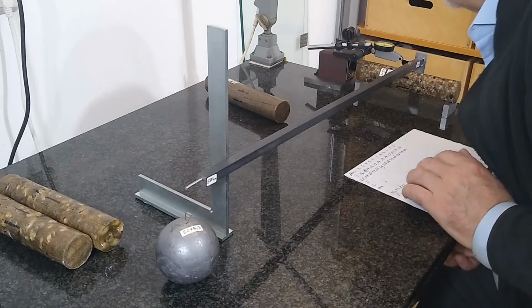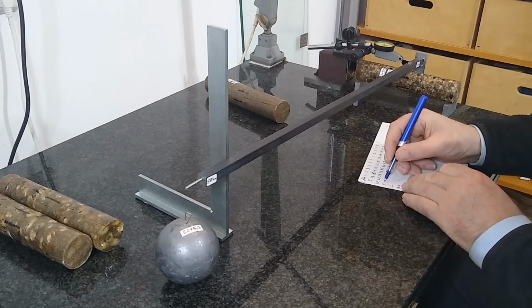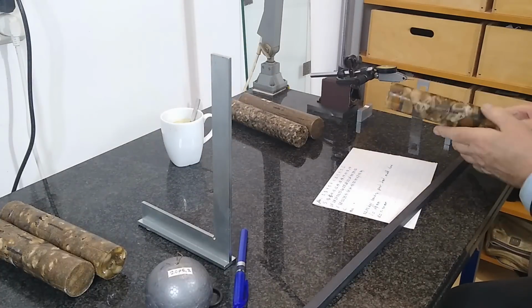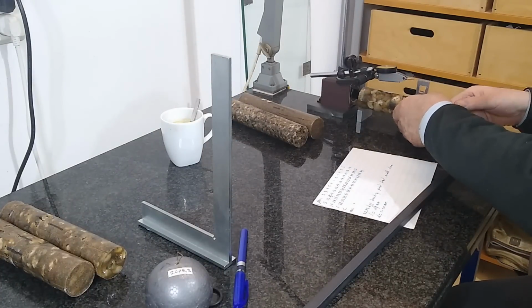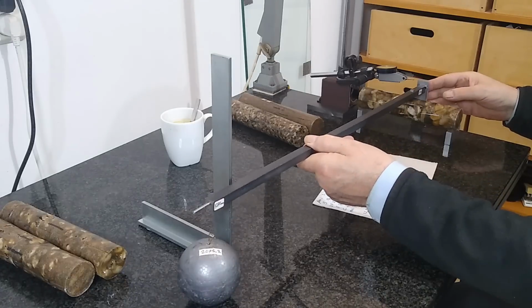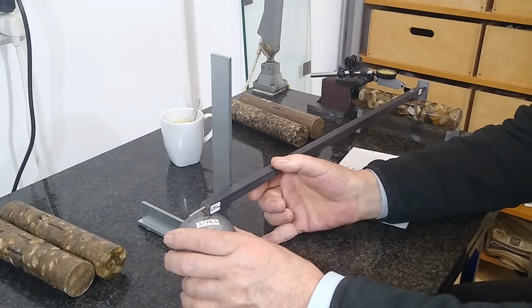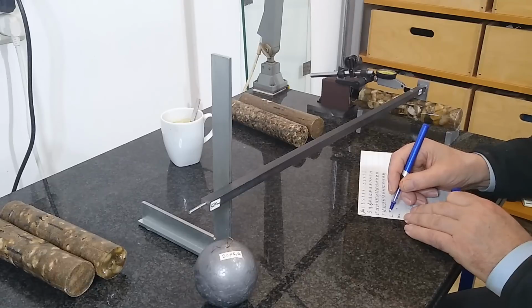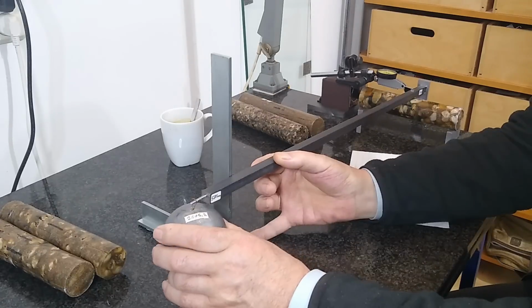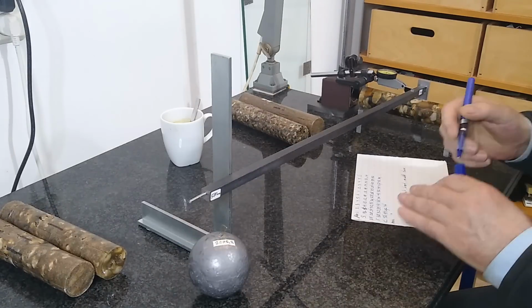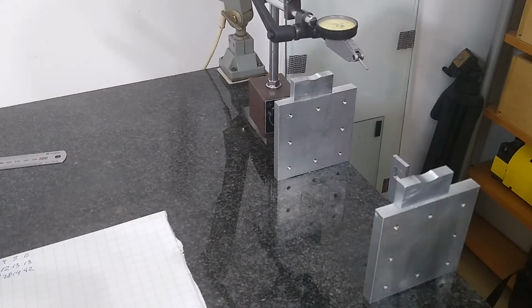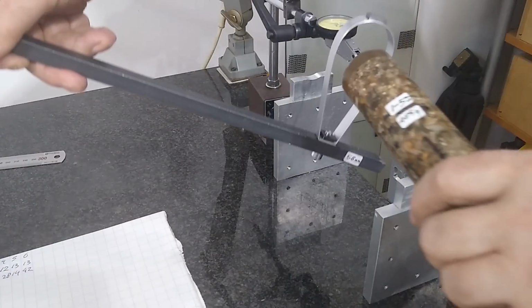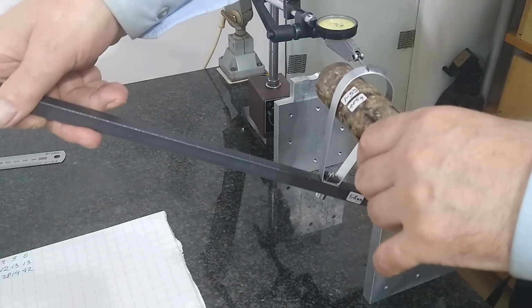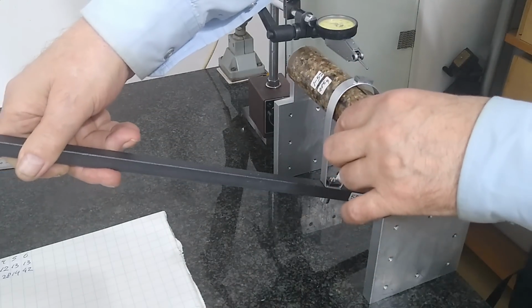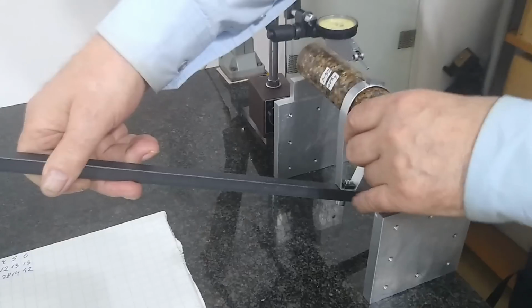And after some thinking, I came to the conclusion that here I am not only measuring the deflection of the rod, but also the deformability of the surface of the test rod. If the steel lever accidentally presses on a pebble, there is little deformation, but when the force is applied to the much more flexible epoxy, it is easily depressed by a few microns. The surface area that absorbs this pressure must therefore be much larger to eliminate these differences.